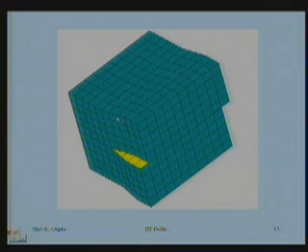But you try to do this here, you keep moving on the same place. You do it here, you do it here, you do it there. These are called the perfect parts of the crystal. Anywhere in the perfect region, if you do this, no problem, you will be there only. You shall keep moving on this plane only. But only when you enclose this region, which is the GH line, in your movement, are you able to go inside the crystal.